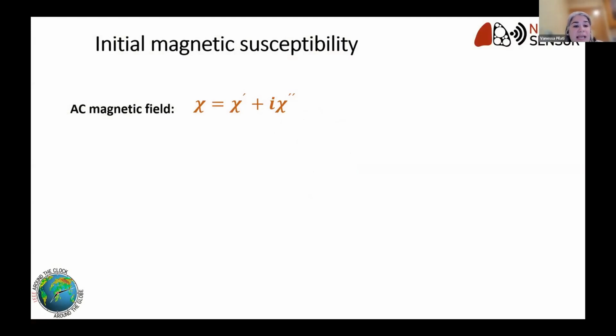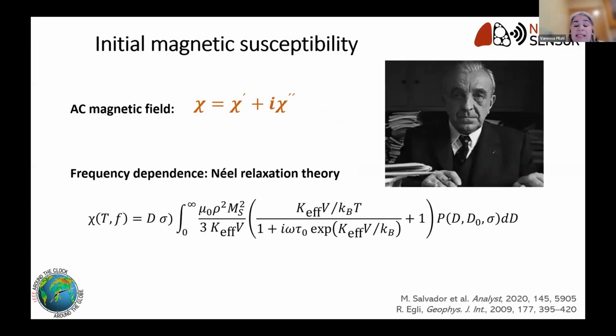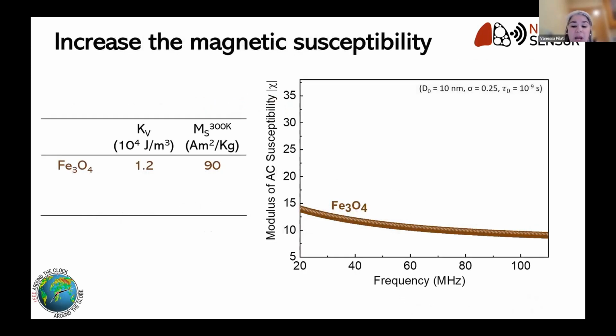Since we have an AC magnetic field, we need to account for the two contributions of the real and imaginary components of the magnetic susceptibility. This is modified with the frequency according to the Néel relaxation theory in the case of superparamagnetic nanoparticles and in the absence of magnetic interactions. Here we introduce the log-normal size distribution that we usually have in our samples. And here is a calculation for the range of frequencies that we operate in our sensor, which is some megahertz. This is the calculation for the case of 10 nanometer magnetite nanoparticles.